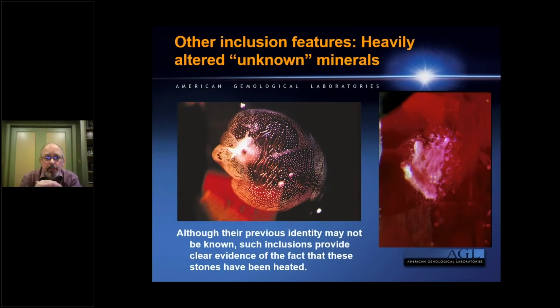Here's another couple of examples. We in laboratories, we as gemologists, we always like to know the identity of the mineral that we're talking about, but inclusion scenes like you see here, both of these provide clear evidence that a stone has been heated, even though we're not able to recognize what the mineral originally was. The mere fact that you see these shows that the stone is heated, proves that the stone is heated. In fact, if you look at the inclusion on the left, this stone has actually gone under more extreme heating conditions. I'll talk about that a little bit later. So you're even going to want to start to ask yourself other questions when you see inclusion features which are so heavily altered as something like this.